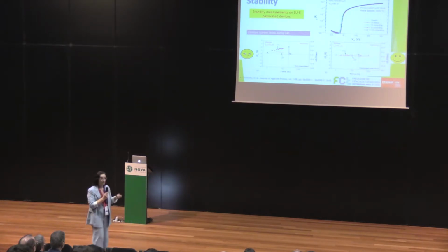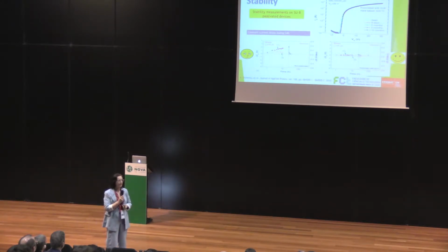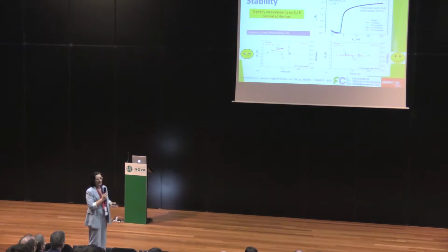But as you know, this type of metal oxide, zinc oxide, and others based on other metal oxides, we use for gas sensor applications because they interact a lot with the atmosphere and with some organics or some volatiles that we want to detect. So in that case, we are using the same materials, but if we use a proper passivation, they are quite stable. We also performed some stress analysis over time, and as you can see, they are quite stable.